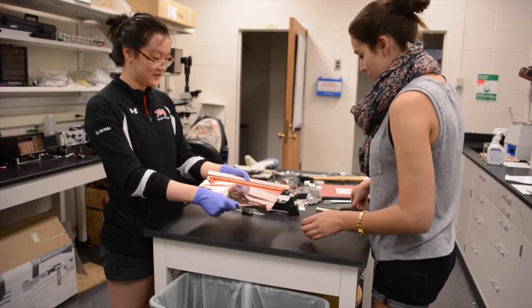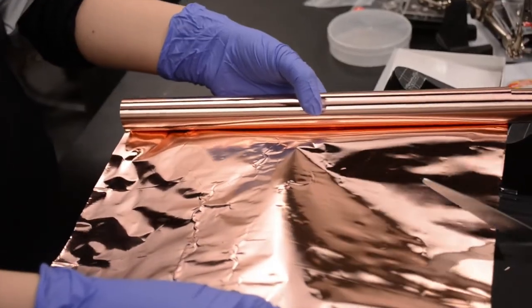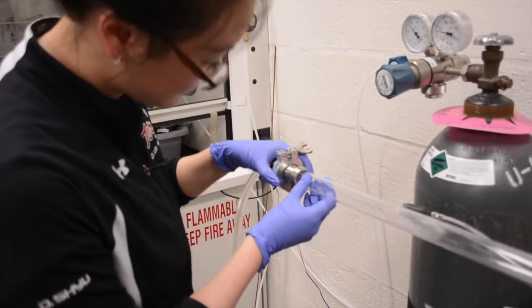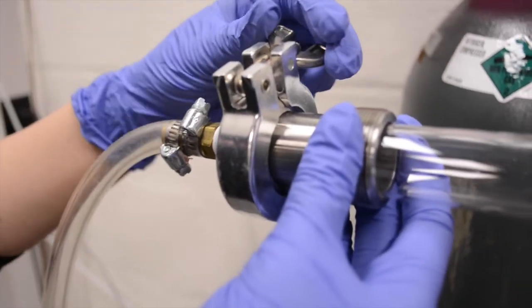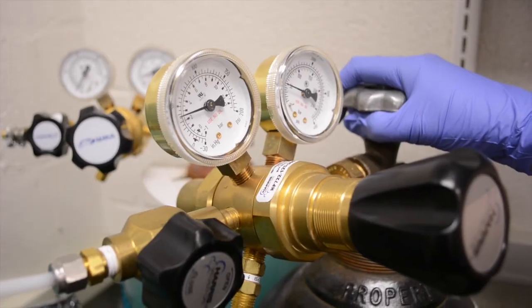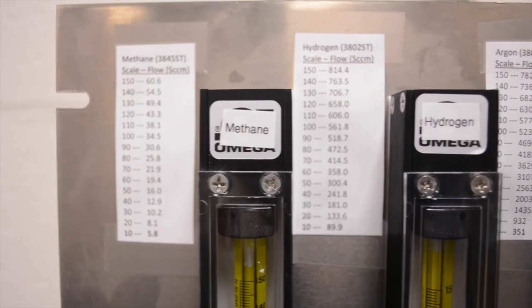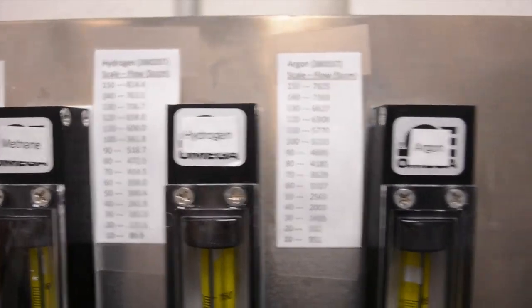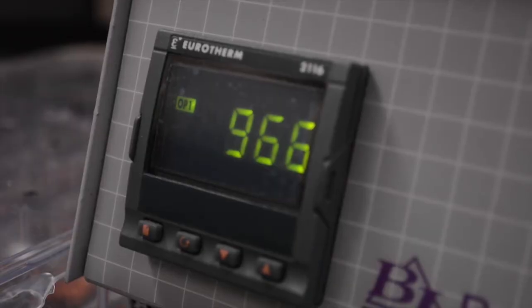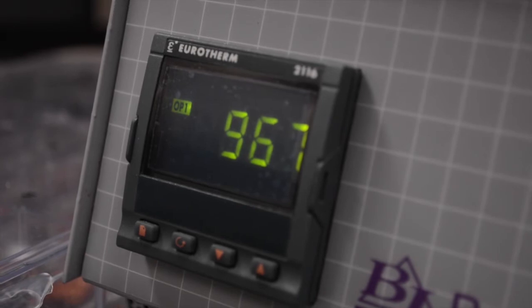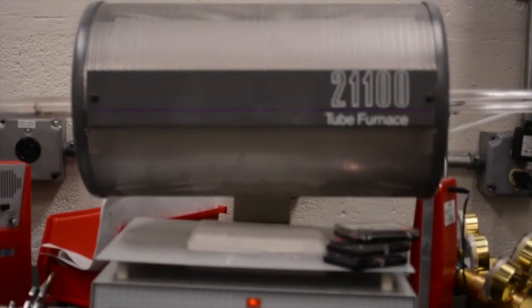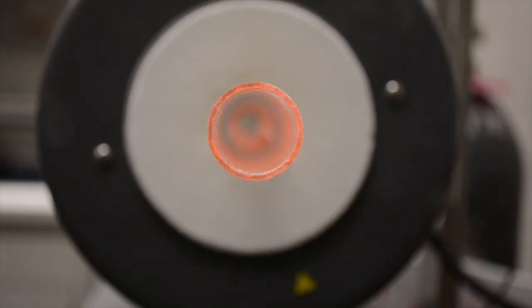Although we initially wanted to purchase graphene, we found it was more cost-effective to produce it in-house. So we decided to grow it via CVD, or chemical vapor deposition. To fabricate our sheets of graphene onto copper foil, we started by purging the chamber with a mixture of hydrogen, methane, and argon. Next, we raised the temperature of the tube furnace to 1,000 degrees Celsius, which created an ideal environment for monolayer graphene growth.